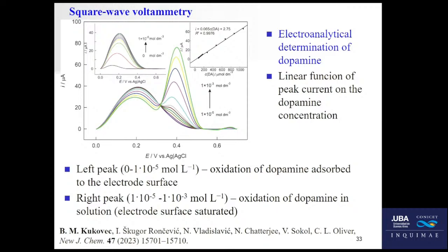If we increase the concentration of dopamine from 0 to 10^-5 mole per liter, the peak current increases for the first peak, that's the left peak. And if we increase the dopamine concentration beyond 10^-5, from 10^-5 to 10^-3 mole per liter, we see that the peak current of the second peak increases, and the first one doesn't increase more.